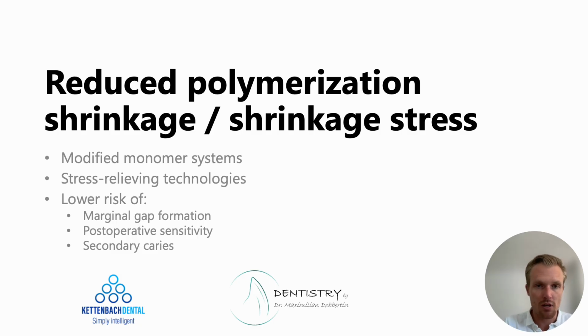same stage, at the same time. So the risk of a secondary caries is way lower than with incremental techniques, because using more layers also produces more potential errors. The post-operative sensitivity is also a lot less in bulk fill composites, and that is not only because of the reduced polymerization shrinkage, but mainly also because of the improved light transmission, and with that the better